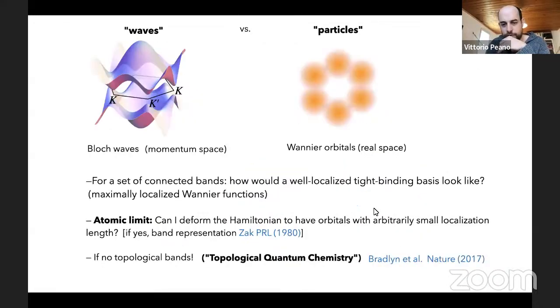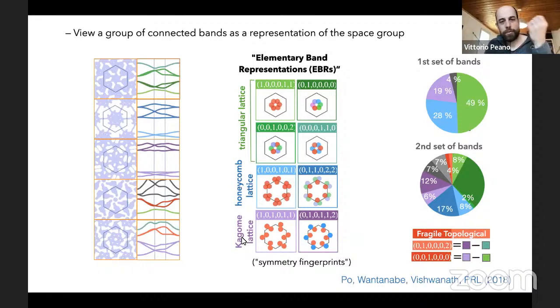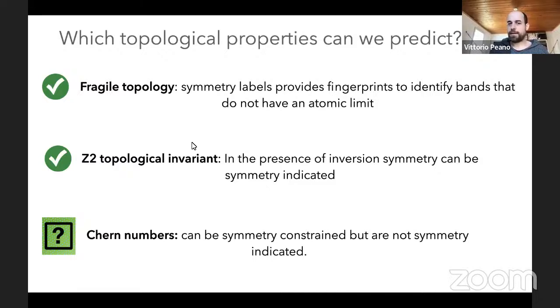This theoretical setting is topological quantum chemistry. For a time-reversal symmetric system with inversion symmetry, the Z2 topological invariant can be predicted directly from the symmetry labels, so our system applies directly. We then asked whether we could also predict Chern numbers, which are more challenging since they are symmetry-constrained but not symmetry-indicated.